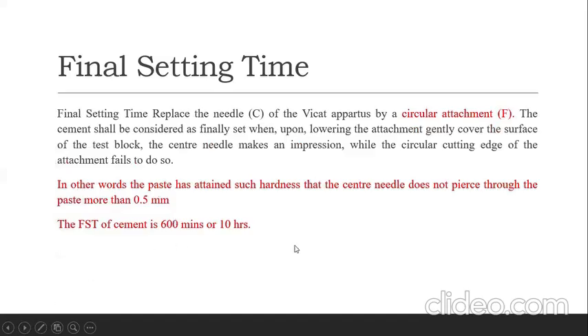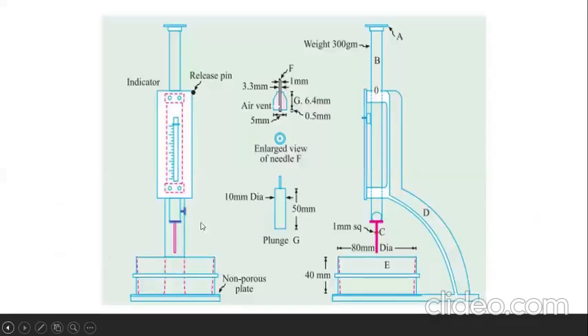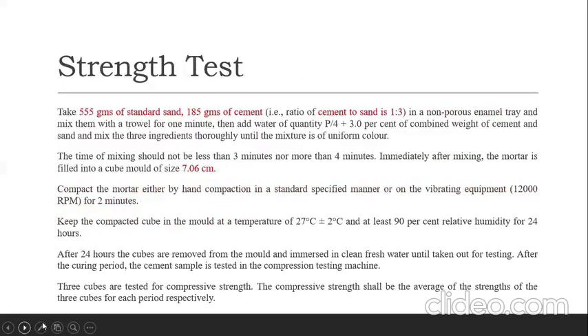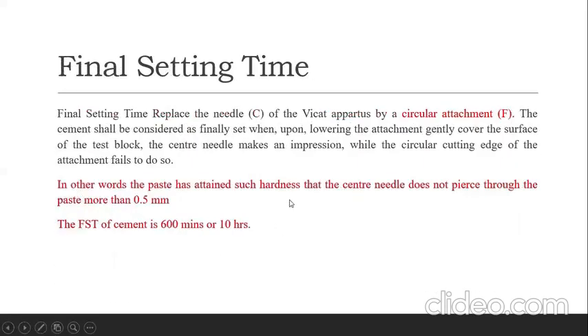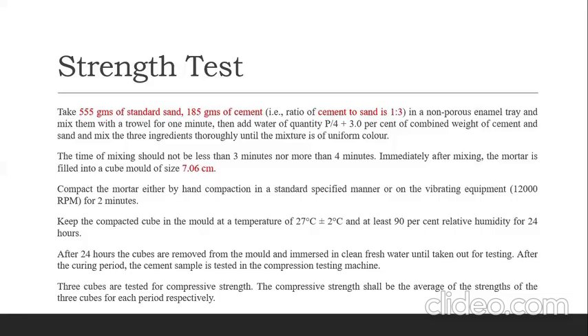Then in the case of final setting time, similarly, the Vicat mold has to be used. Here, in addition to the needle, we have to use a circular attachment, which is shown in this figure. See, this is a circular attachment. You have to attach it to the bottom of the needle, and allow this needle to pass through it. And you have to check that the penetration is not more than 0.5 mm. If it is not going 0.5 mm, then the cement has reached the final setting time. Generally the final setting time of cement is estimated to be 600 minutes, or 10 hours, for ordinary Portland cement. Then next is the strength test.